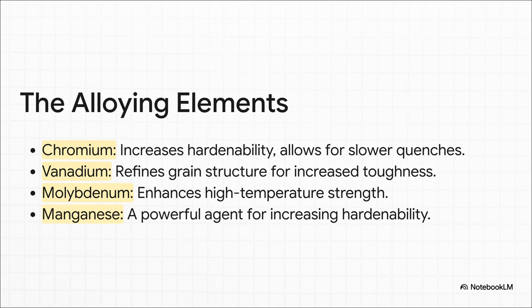Think of things like chromium, which actually buys us more time during that critical cooling phase, or vanadium, which helps keep the internal grain structure fine and tough. You've got molybdenum for high-temperature strength, and manganese as a powerful hardening agent. These little additions are what make the difference between just plain steel and a high-performance tool steel.